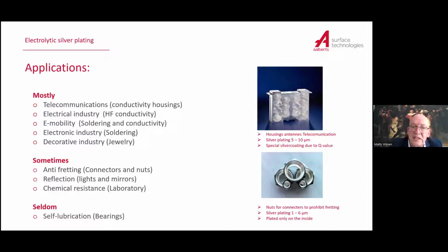Another thing, and that's where we use it, is for the anti-fretting purposes. For anti-fretting purposes, we silver plate nuts, and these nuts are used when you put, for instance, stainless steel and stainless steel together, and you have some vibrations alongside. After a while, the stainless steel will, in principle, weld to each other. You won't get it loose anymore. Putting a coating in between, like silver, which has a very low coefficient of friction with easy turns, makes sure that the fretting doesn't occur.